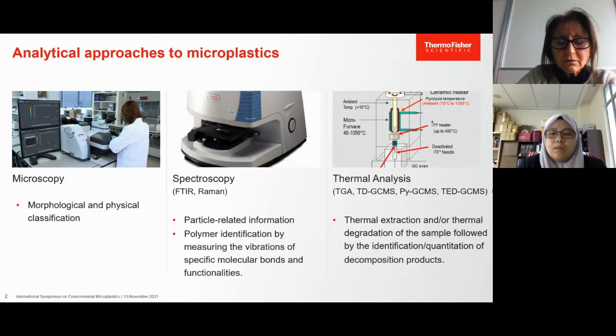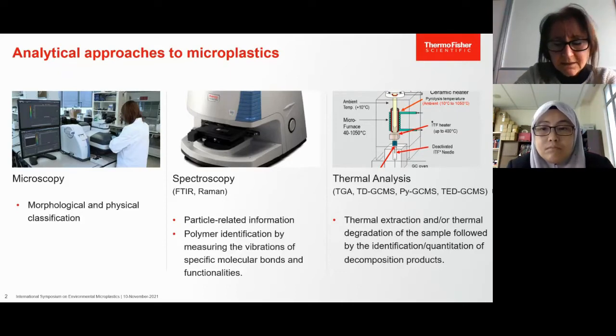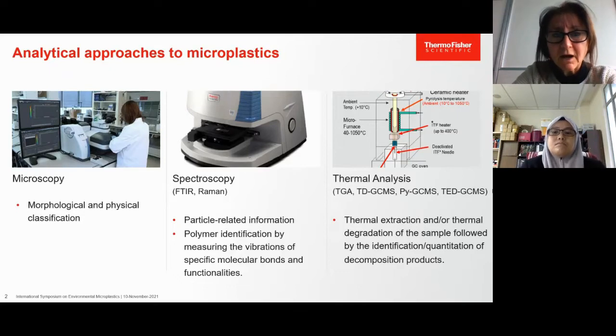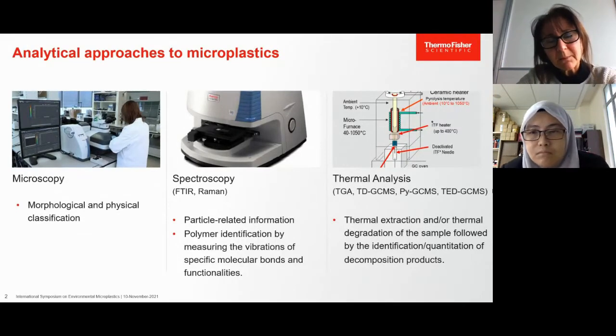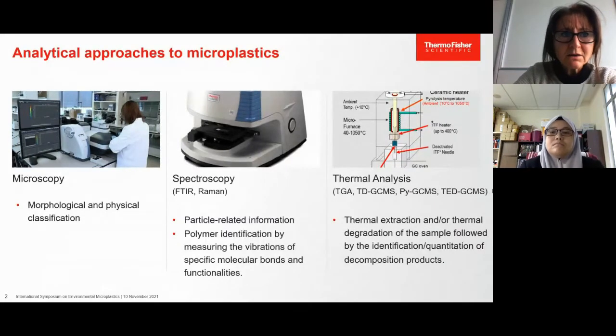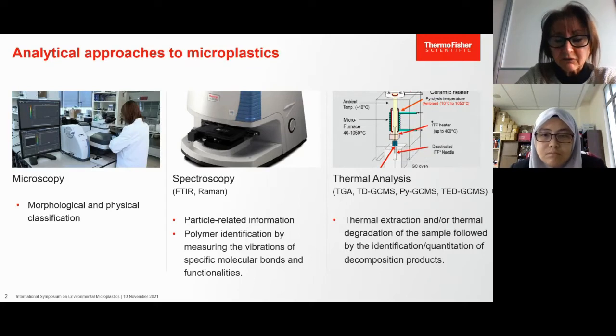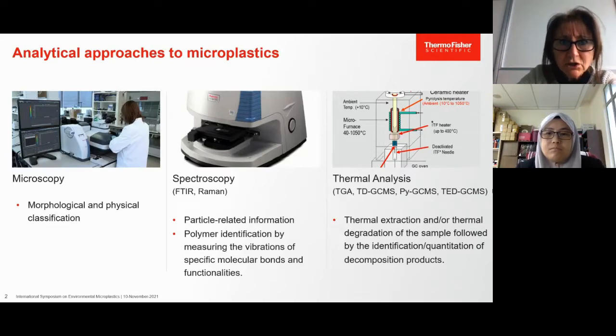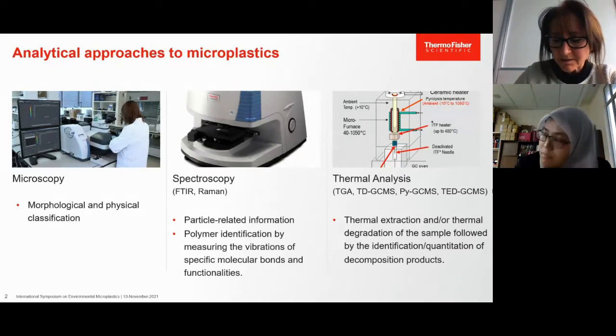The detection through the GC-MS allows to identify and quantify the amount of microplastic through the characteristic thermal degradation products and their respective indicator ions. One benefit of the thermoanalytical methods is the capability to detect bulk amounts of micro and nanoplastics much below the lower size limit of microscopy and spectroscopy techniques, offering very low detection limits in the range of picograms to micrograms.